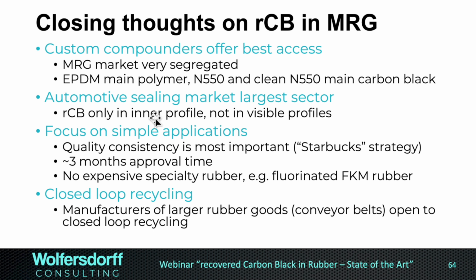We also need to focus on simple applications, because in some applications we, for example, have very expensive rubber, fluorinated FKM rubber, where recovered carbon black needs to perform very highly, and those companies don't want to have any industrial waste if things don't go well during production. So recovered carbon black, until consistency has been proven, should really stay in simple applications. We got 3 months approval time, typically for non-tire rubber. And again, consistency. The Starbucks strategy is super important. Some manufacturers of the larger goods, like conveyor belts, might be open to closed loop industrial recycling, where the pyrolysis company or recovered carbon black company takes in industrial waste, which can be led back into their own products.